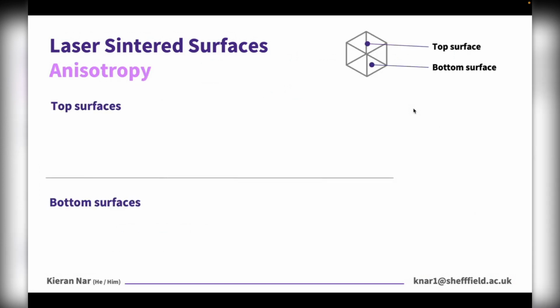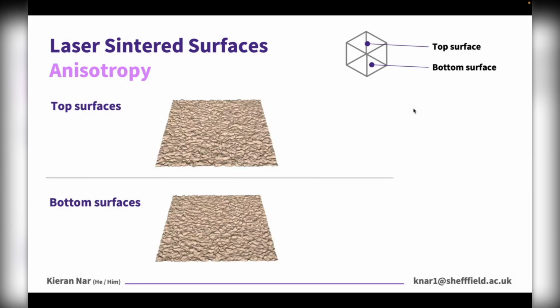And what we found when evaluating the top and bottom surfaces of cube-shaped specimens were as follows. So before I get into the numbers, these scan images qualitatively describe each surface, and I'm sure you'll agree there are no marked visible differences between them. And similarly, when we look at their resultant RMS or Sq roughnesses, we discovered that their surface heights typically vary by the same magnitudes.